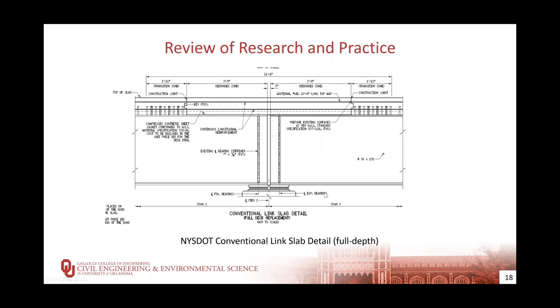Here are a couple of typical details, both taken from New York drawings. In this case, we have a conventional concrete link slab. You can see that there's about a 3.75 feet debonded zone on either side of the joint. I will say both of these are for steel bearings. This was for a case where the entire deck was replaced, so it's almost like new construction. You then have a transition zone at each end where the link slab is tying into the existing reinforcement. For the conventional concrete slabs, we see a full depth replacement, a full depth link slab, and the debonding at the bottom of that link slab.